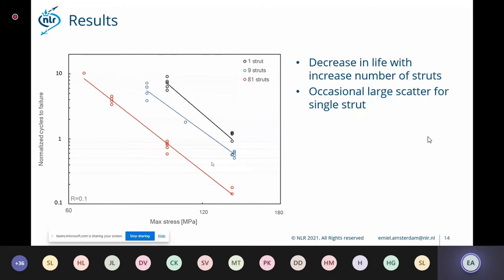So that's remarkable. Here you can also see that for the single strut specimens, 3 results are almost the same, but they show some scatter. So occasionally there is one specimen with an extra low life. That's also typical for fatigue, especially for fatigue of additive manufactured materials, where you can occasionally have a large defect in the specimen or in the material. So those are the 2 things that we can see right away.